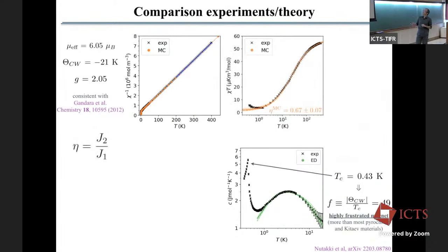Next, the next thing is this susceptibility. If you plot it as chi susceptibility times temperature as a function of temperature, we see a clear evolution from a high temperature Curie-Weiss fit to a low temperature Curie law, which corresponds to a spin liquid Curie law. I'm not going to go into details here, but this gives us many data points to compare experiments to simulations, in particular to classical Monte Carlo.